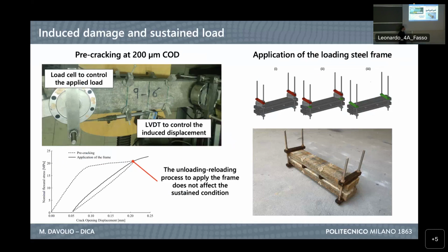So this frame was exposed together with the specimen, as you can see from here. And the load was applied first on these load cells positioned on the top of the specimen with these steel bars, was then transferred from the load cells to the specimens, tightening some nuts we positioned here below the red ones and above the green ones. And in doing this, the load was transferred and the load cells could be released and moved to the following specimen.